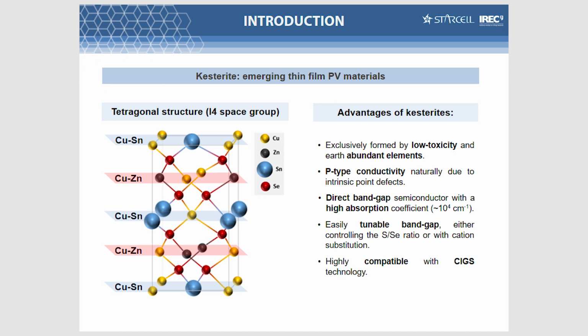low toxicity and abundant elements, normally exhibits p-type conductivity, and has a direct band gap, so we need very thin layers for absorbing all the sunlight, and we can play with the composition and tune the band gap. This is very relevant to adapt the band gap of our material for different applications and advanced concepts, and of course it is highly compatible with CIGS. This means that a company producing CIGS can easily shift to Kesterite.